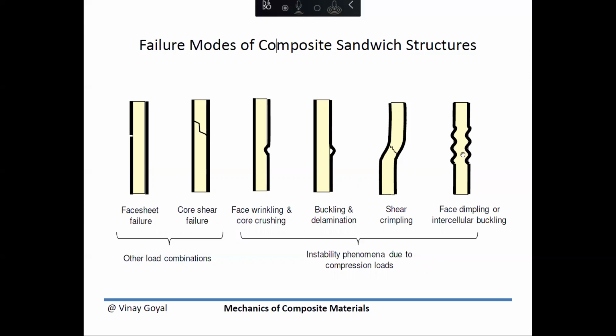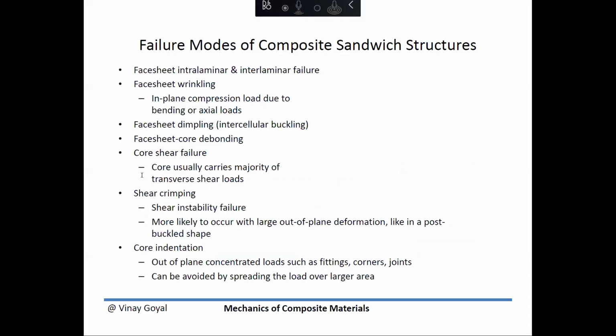And then you can have a situation where the cell size is large enough and the compression stress is large enough where locally the face sheet buckles. And all these ones are considered instability phenomena due to compression loads. These ones can occur when there's high shear loading. These ones can occur when there's high bending stresses. So the failure modes can be quite significant.